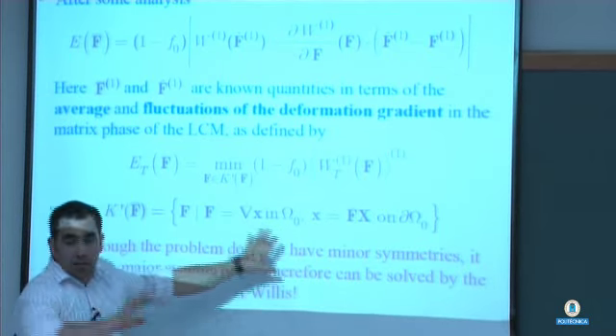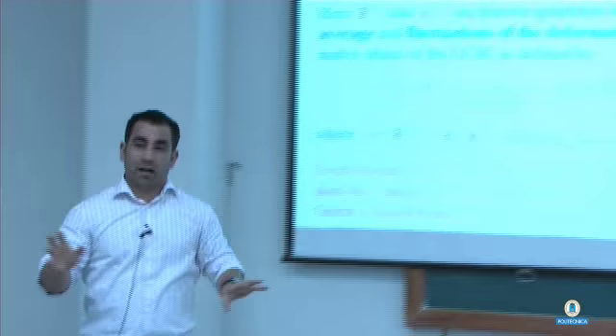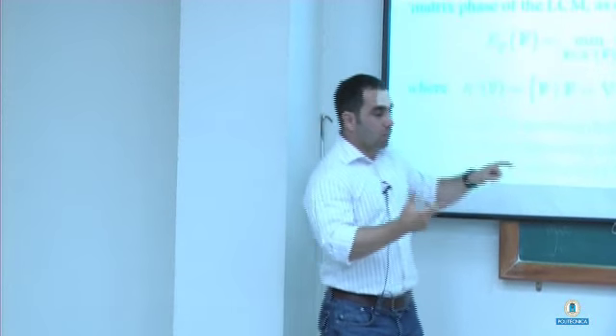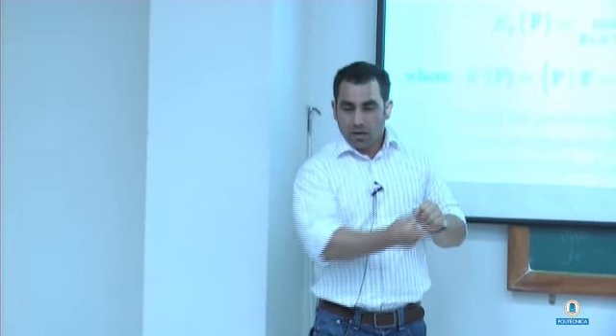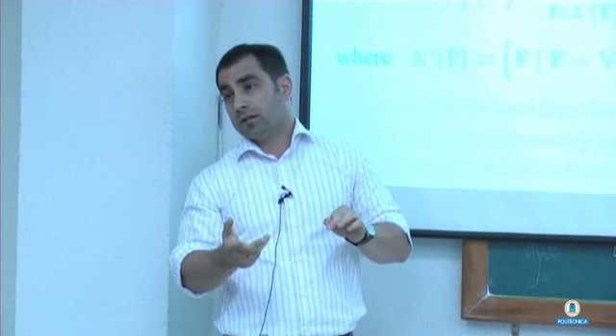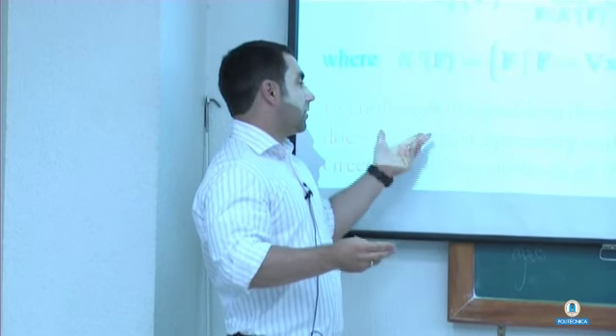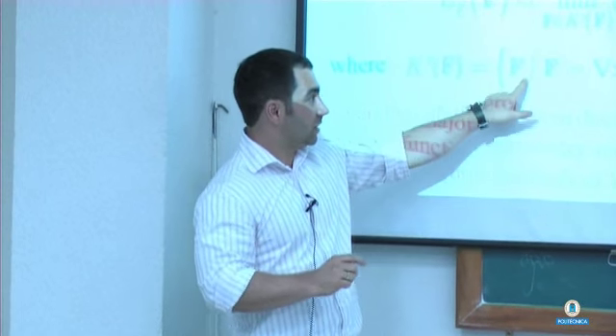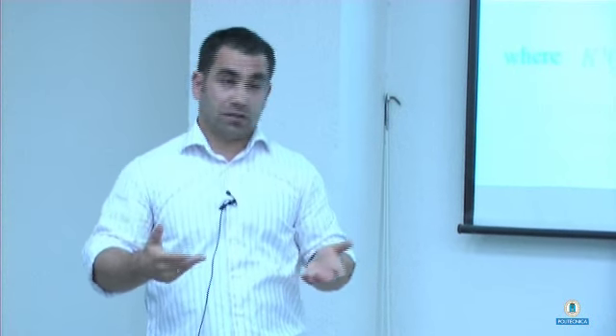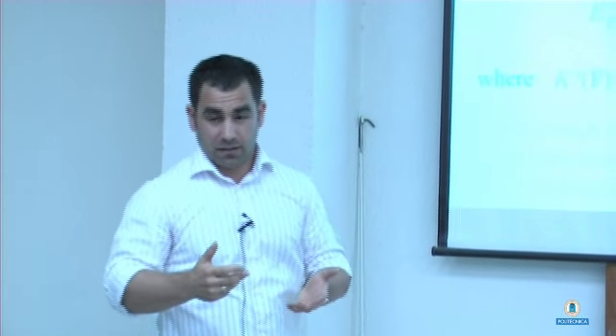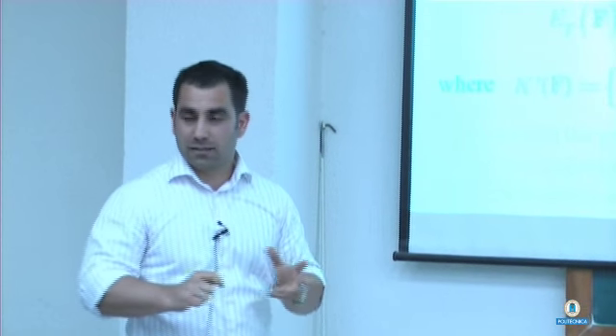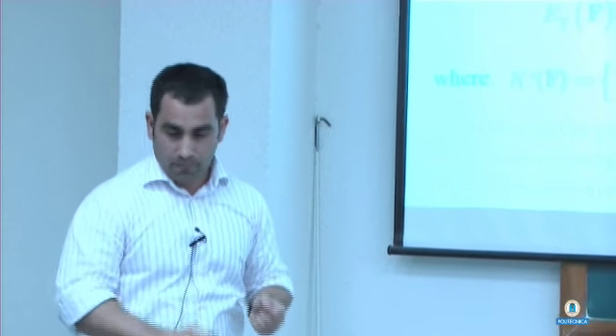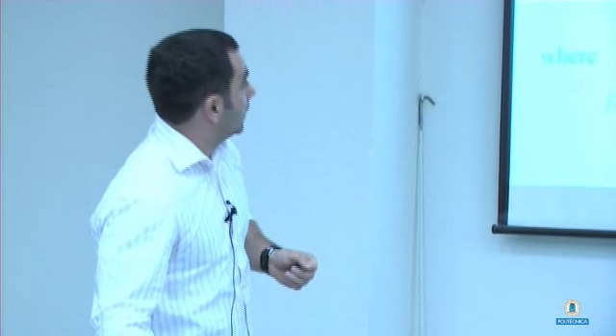Now, given that we have got rid of this J greater than 0, what do we have? Well, we have a larger set. So at the very worst, in the worst case scenario, we have a lower bound to the solution that we want. And it is also possible to look at whether the solution that you obtain doing this has the determinant of F greater than 0. In that case, a posteriori you can check that the solution is the solution that you want. Okay? So in some cases, you're going to have exactly the solution that you want. In some cases, maybe pathological cases, you may not. But still you have a lower bound. Okay? All right. So that's the energy.